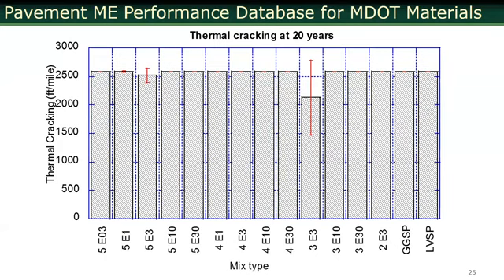Now for thermal cracking, we saw nothing. For all the thermal cracking, we were using a single K. They were all predicting the same, regardless of the mix type. And this is the type of problem even MDOT was experiencing. So we actually see that the 4 mixes perform better than the 5 mixes for thermal.